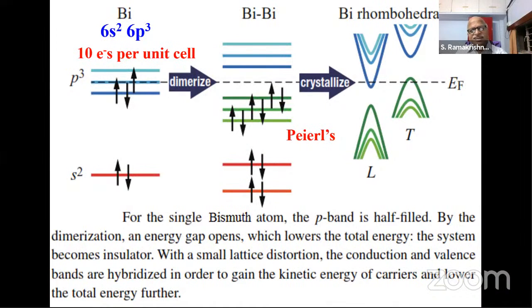It undergoes a small lattice distortion. Instead of cubic, it becomes rhombohedral. And the important thing is that at two different symmetry points, the bottom of the conduction band is lower than the top of the valence band. So there is an energy overlap if you consider these two valence and conduction bands. And that is the important criterion of bismuth. The unusual properties stem from this fact that the conduction band is lower than the valence band in this system.